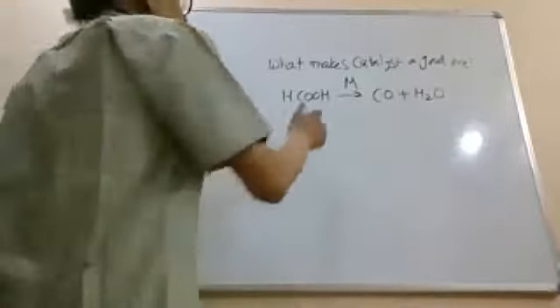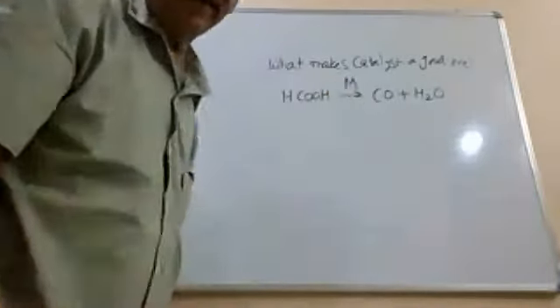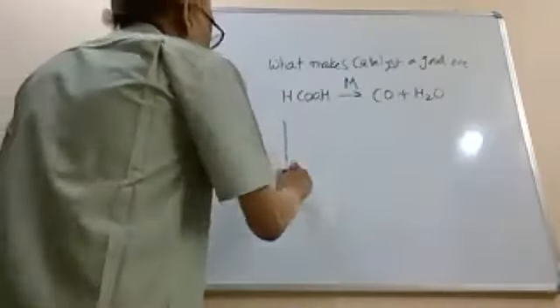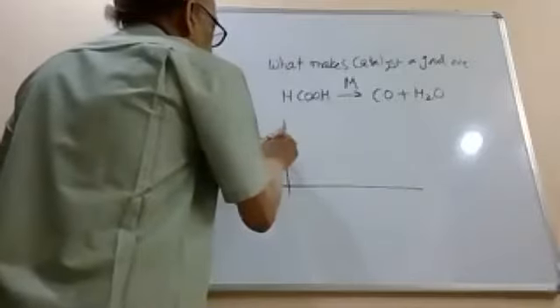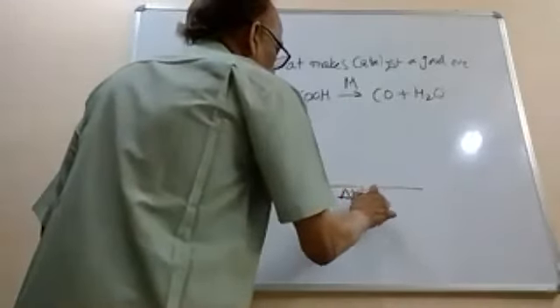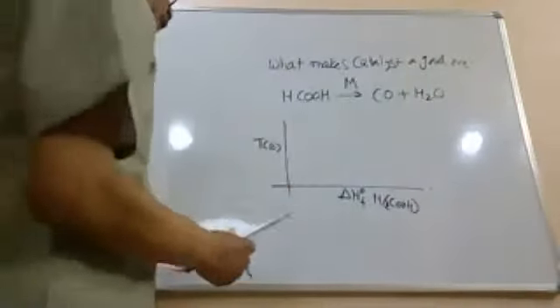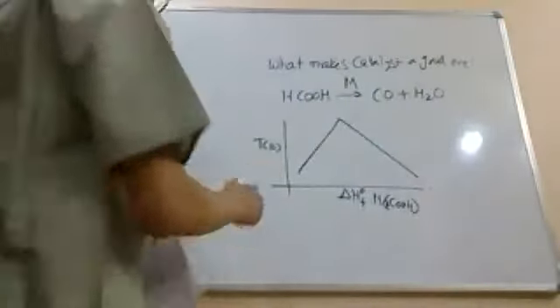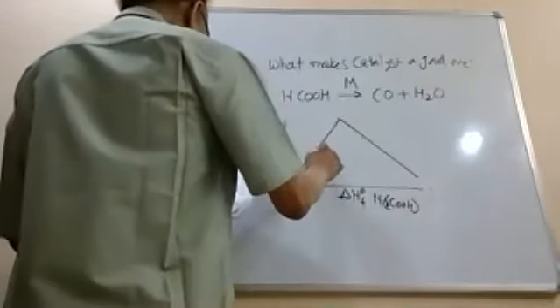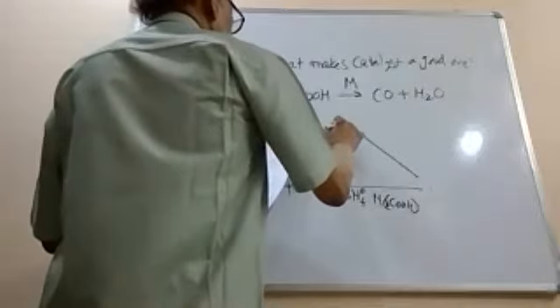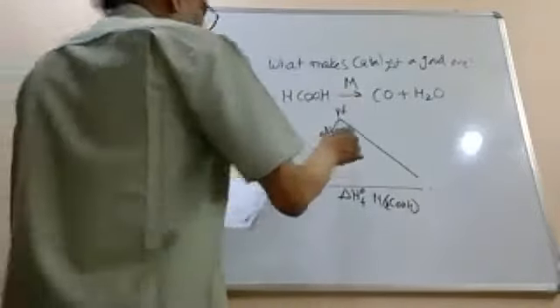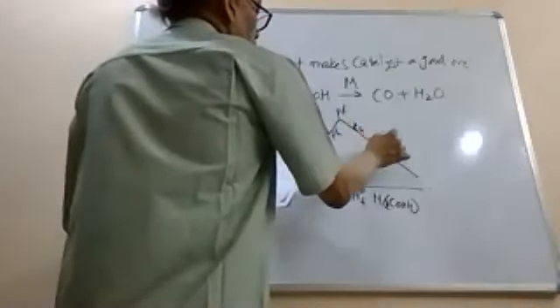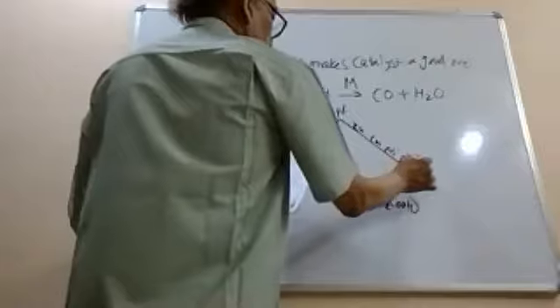And what they have done is they looked at the heat of formation of the metal formate and the temperature of the decomposition and plotted a graph: temperature of decomposition and delta H 0 of the metal formate complex. What they found was when you do different metals, you have a volcano-shaped graph here. On your left-hand side, you have gold, you have silver, you have palladium, you have rhodium, and you have platinum on the top, and you have ruthenium, copper, nickel, iron, and tungsten.